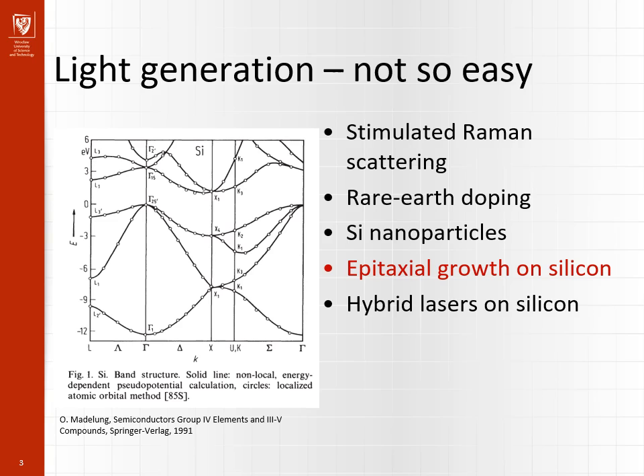Among semiconductors, 3-5 alloys are already commonly used and well developed for light-emitting applications. However, their lattice constants do not match the lattice constant of silicon, so their direct epitaxial growth on silicon doesn't seem to be a method to easily make light-emitting diodes or laser diodes. Currently, a popular and promising method of involving 3-5 semiconductors in silicon-based devices is to attach 3-5 structures by bonding to silicon structures. However, it is a challenging method.